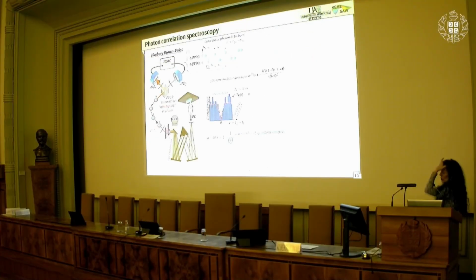So to actually confirm that we are dealing with quantum light, what we did then is we studied the statistics of the emitted photons. We did it by filtering the luminescence from these nanowire quantum dots using a grating monochromator, and we then directed it to a standard Hanbury Brown and Twiss interferometer that delivers a histogram of correlation events that is proportional to the photon correlation function.